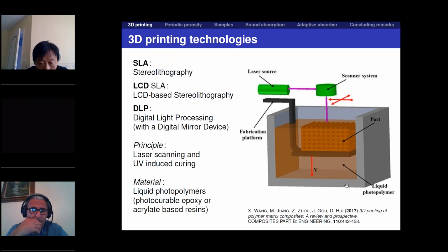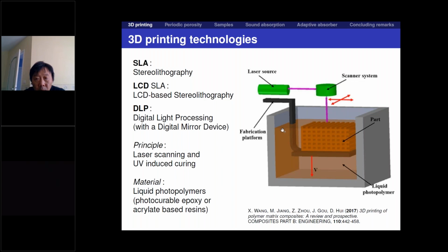And here we have a container which is filled with the liquid photopolymer, and we use a laser beam to solidify some small bits, let's say voxels, of this photopolymer resin. We do it first on the fabrication platform, which is submerged in this resin, and it is moved down by a very small distance of the layer thickness when the whole layer is 3D printed, and the whole process can be repeated.